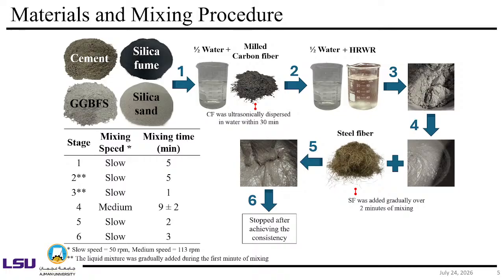So, low carbon. And then we use milled carbon fiber. Milled is the key word here. Instead of traditional commercial carbon fiber, which is again not low carbon at all, we use milled carbon fiber. That is commercial carbon fiber waste from carbon fiber manufacturers, from Boeing, BMW, wherever carbon fiber is produced. So again, low carbon. We mix milled carbon fiber into water, and then add superplasticizer to increase the workability, because these carbon fibers can be really small in particle size, and because of van der Waals forces, they could make the concrete mix very dense and not fluid. So we add superplasticizer to increase the workability, and then we mix it, and then we introduce the steel fiber, and then mix a little more until we achieve a consistency in the concrete matrix.